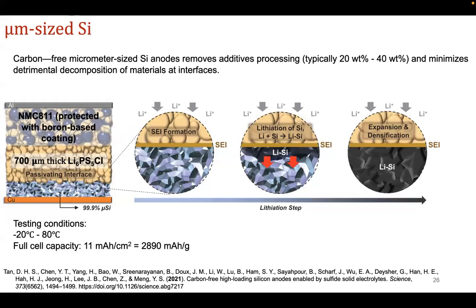And so what you see is that under these testing conditions, in pretty extreme temperatures, from negative 20 degrees Celsius all the way up to 80 degrees Celsius, you can achieve pretty high full cell capacity that is much higher than typical lithium ion battery capacities. Okay.